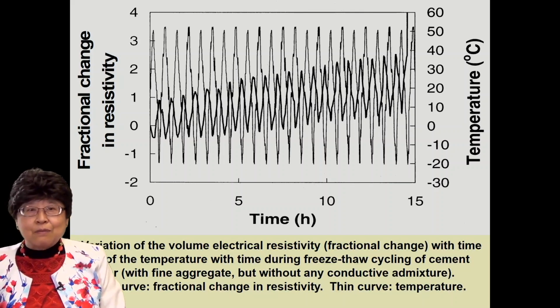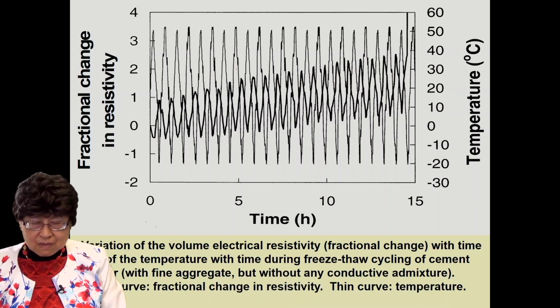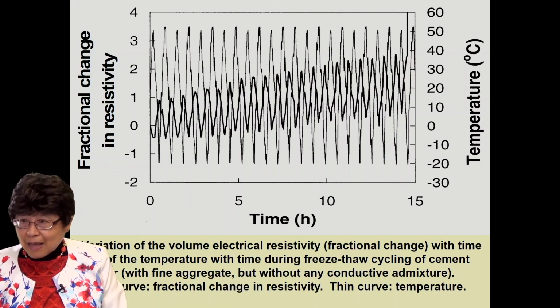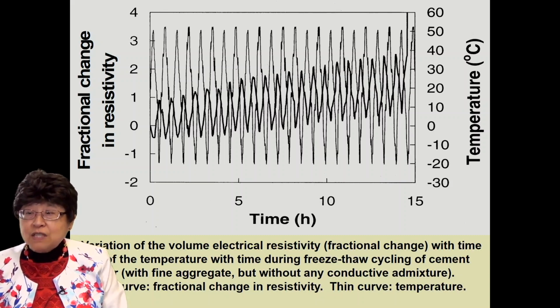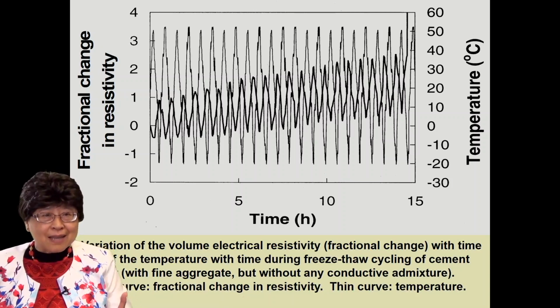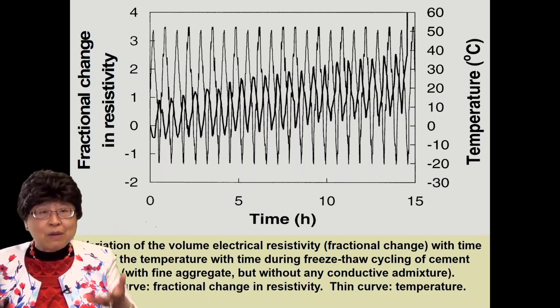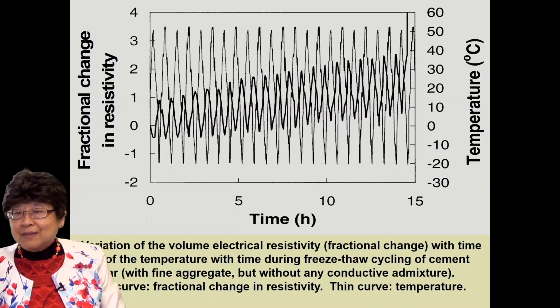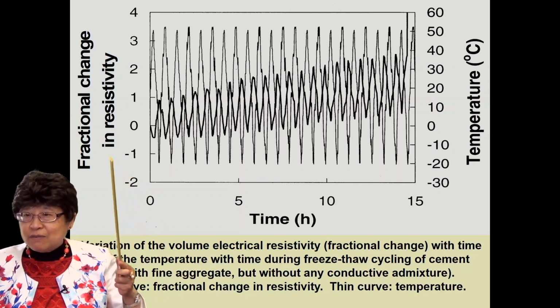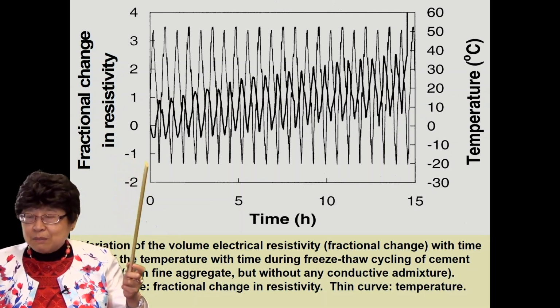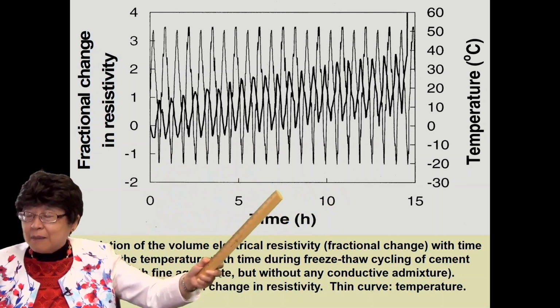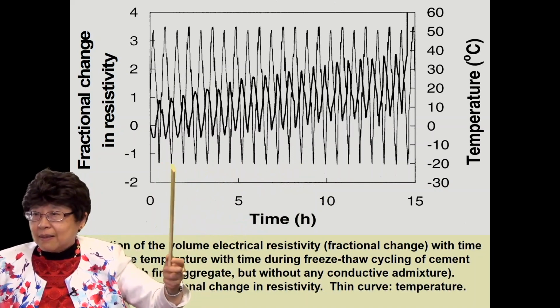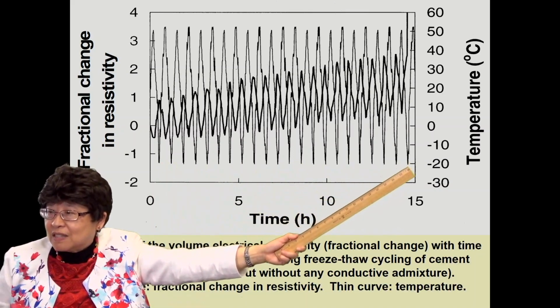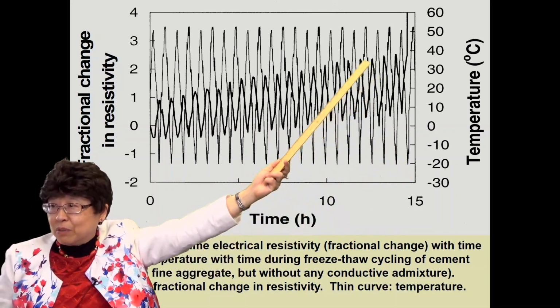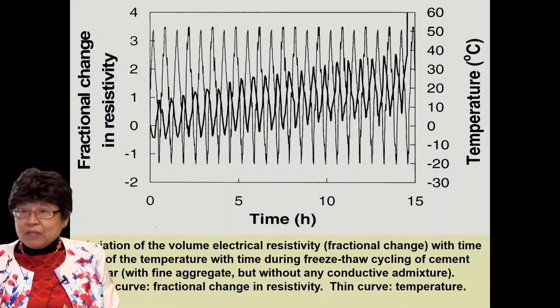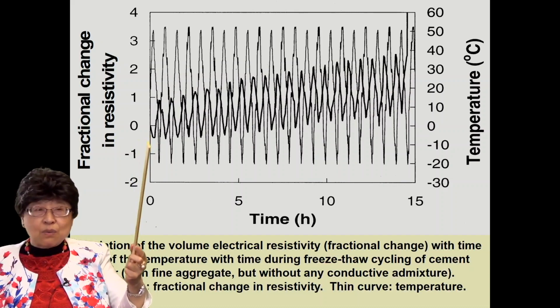Now, the cement resistance also reflects the temperature, in addition to the damage inflicted by what's called freeze-thaw cycling. Now, cement gets damaged because of cycling between freezing and thawing temperatures. Okay? So here is the fractional change in resistivity. It's under uniaxial compression, and it's versus time, but the temperature is cycled, as shown by the thin line, cycled between freezing temperature below 0 and thawing temperature above 0. Okay? And every time the temperature increases, the resistivity goes down.